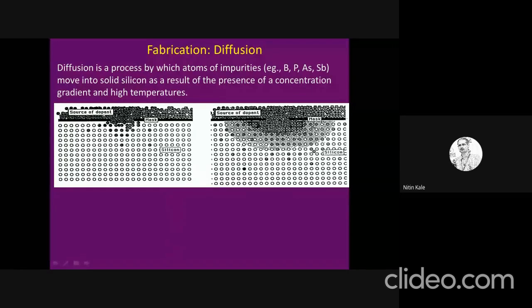And now you put a source of dopant here. It could be another wafer of, let's say, boron. So there is a silicon wafer and there is a mask. The mask could be a reasonably thick oxide or nitride, and you have an opening in the mask. You put it in a furnace and raise the temperature. Now these dopants are going to diffuse. Boron has a very high diffusivity, so it's going to diffuse, and you will have a profile of boron in the silicon, which is something like this. And the rest is something that you would know: boron and silicon form a bond, and it would leave a hole behind, and that now becomes a charge carrier. Any questions on this diffusion?